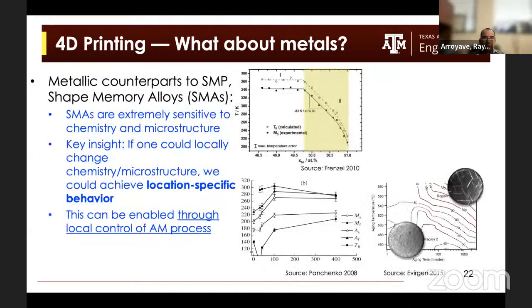Now, one interesting aspect of shape memory alloys is that they are extremely sensitive to minute changes in the chemistry and the microstructure, right? So here, for example, I have a plot for the transformation behavior, basically the transformation temperature, at which temperature this reversible transformation is triggered for nickel titanium as a function of the amount of nickel. And if you look at this change, you can change the transformation temperature by almost 100 degrees Kelvin by changing the chemistry by just less than 1 atomic percent, right?